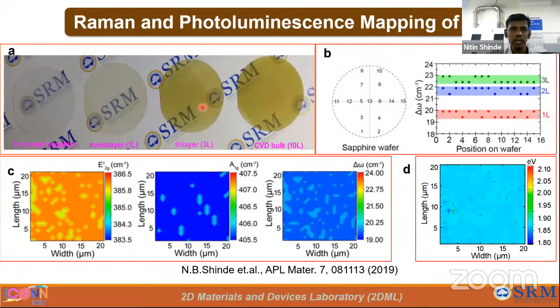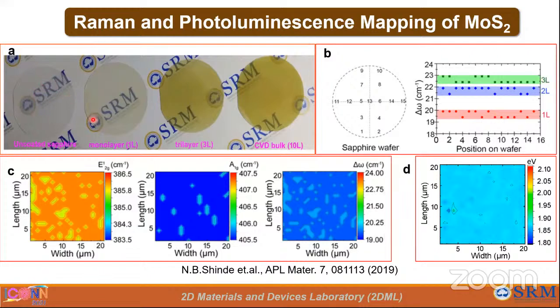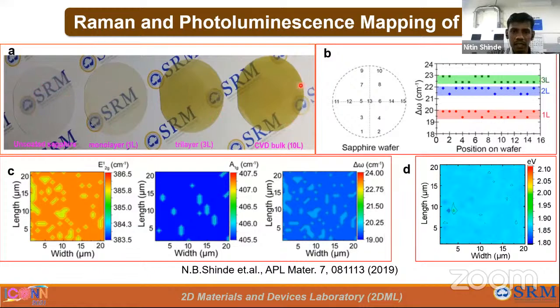We can see here an actual photograph of our synthesized 2-inch wafer. Our main objective is the synthesis of large area MoS2 on wafer scale. This is an uncoated sapphire wafer, and this is a monolayer, trilayer, and this is CVD bulk.